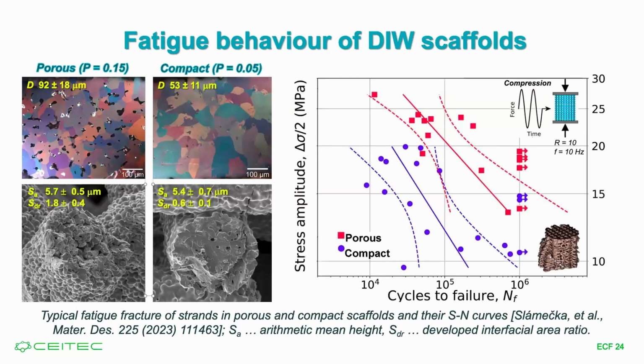And then we tested these materials under fatigue, and the surprising thing is that the porous samples with microporosity are much better. You can see here, for instance, at this level, the difference in fatigue life between them is 1 order of magnitude. And they differ in grain size, in microporosity, as you can see, also in surface roughness. But the conclusion is that the reason why these materials are much better is this interaction of cracks with pores, which leads to really highly tortuous crack paths, and this results in improvement in total fatigue life. Actually, crack initiation is faster in these materials, and I talked about that yesterday in more detail, so I'm not going to talk about it more here.